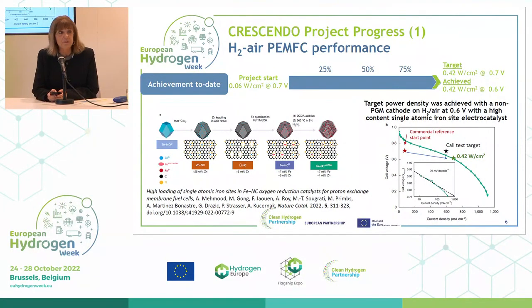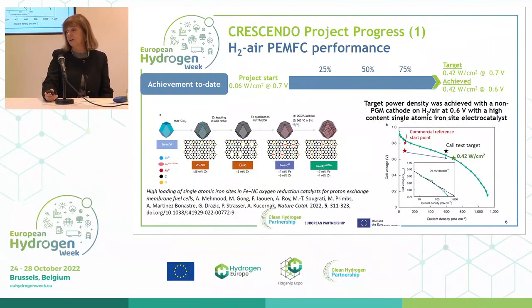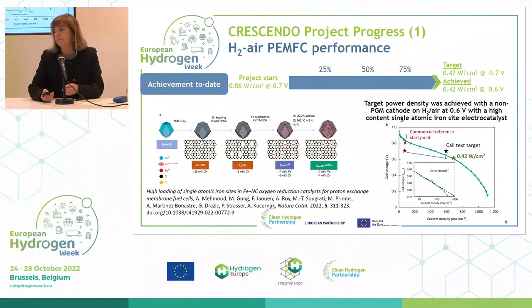A lot of different developments. I'm not going to take you through all of the different carbon materials, supports, microporous, mesoporous, heteroatoms, different ways of inserting those elements. But by the end of the project, you can see that in terms of the power density, we achieved the target, 0.42 watts per square centimetre. It was at 0.6 volts and 0.7. It's nevertheless still relevant in terms of the application. That reference point there is certainly relevant in terms of automotive application.